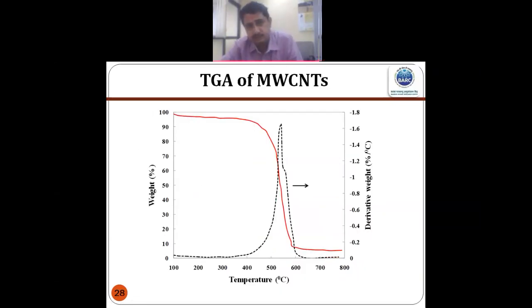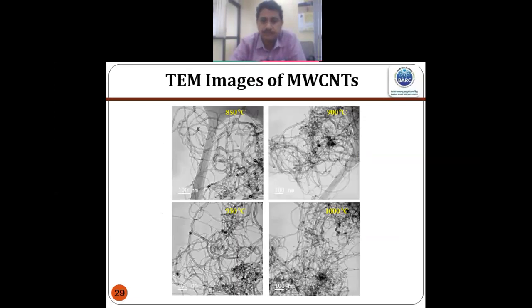Also, we do the thermogravimetric study. Why is it required? To understand how much amorphous carbon has been deposited. If this is a typical multi-wall carbon nanotube, and I take the DTG, that means the differential of TG, here we can see two peaks. This peak is related to the high energy configuration, like the end cap of the carbon nanotube or the defective part, that gets oxidized first, and the second peak, this one, is due to the wall of the carbon nanotubes.